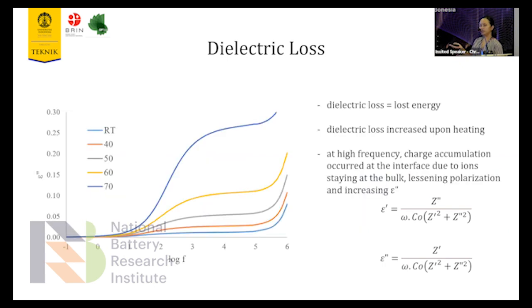And this is what we have from the analysis of dielectric loss from the frequency and the epsilon double prime or dielectric loss. We see that the dielectric loss basically is the energy wasted into heat. So it cannot be stored as more energy. And here we can see the trend that the dielectric loss is increased upon heating. This shouldn't be happening, but at high frequency, charge accumulation occurred at the interface because the ion is staying at the bulk. It does not move, and it is lessening polarization. So less ions is mobile between two electrodes, and thereby it is increasing the dielectric loss.